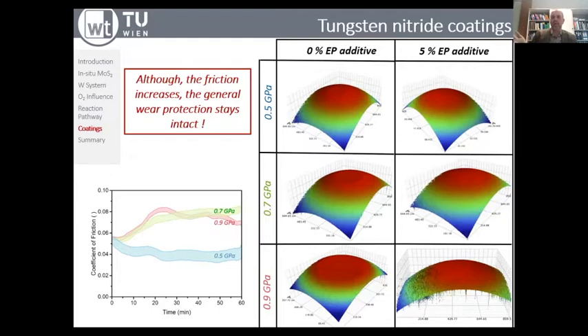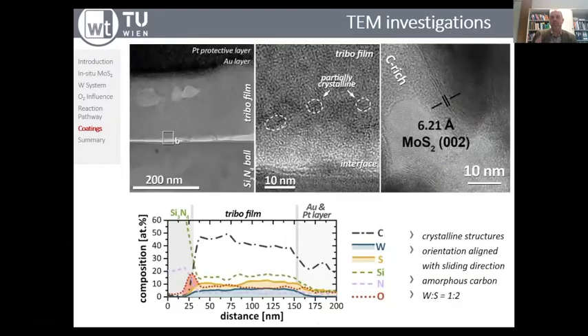If you add the additive, it really reduces, even for higher contact pressures, the wear on the counter body. But as I said, this is one part of the truth. The other part is actually directly connected to the structure of these, let's say, fragments that are formed in the tribofilm. So we did some TEM investigations, and you can see that most of the things that we observe are